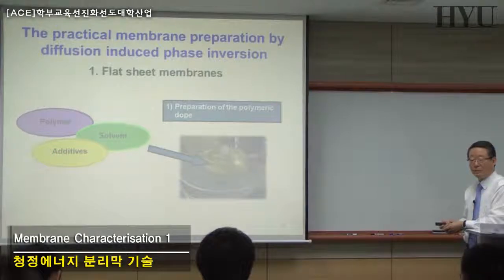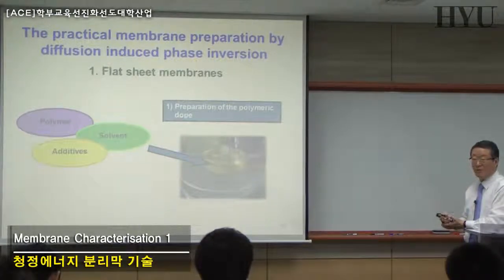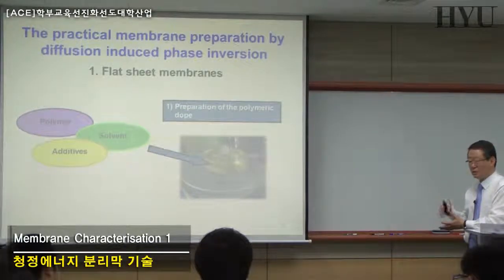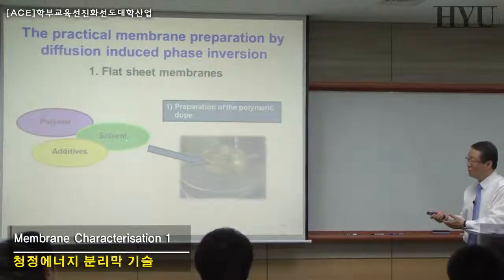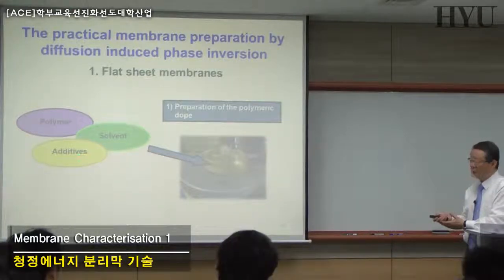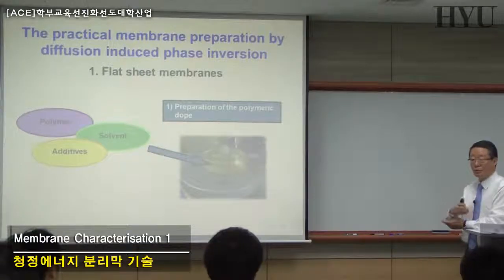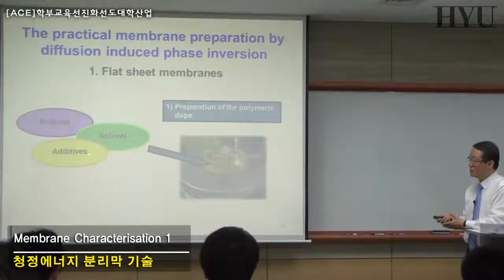Additives may be ethylene glycol or the pore forming agent, or it could be the viscosity enhancer, if you're concerned about the low viscosity for a selected solvent system. Okay, so additives may not be just one component, but depending upon the producer, depending upon how you have to prepare the very well-defined hollow fiber or flat sheet or whatever, this should be selected.